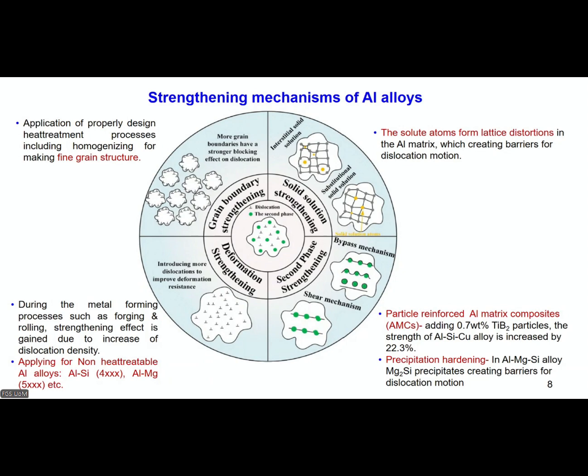There are basically two types: particle reinforced aluminium matrix composites, for example adding 0.7 weight% titanium boron particles, the strength of aluminium, silicon, copper alloys increased by 22.3%. And precipitation hardening, in aluminium 6063 alloy, magnesium silicide precipitates create a barrier for dislocation movement. In all these cases, the precipitates make a barrier for dislocation movement. That is how it gains this strengthening effect.